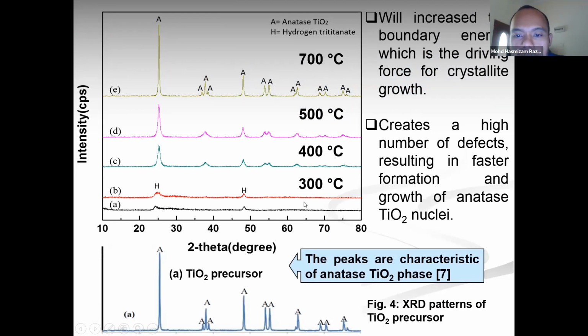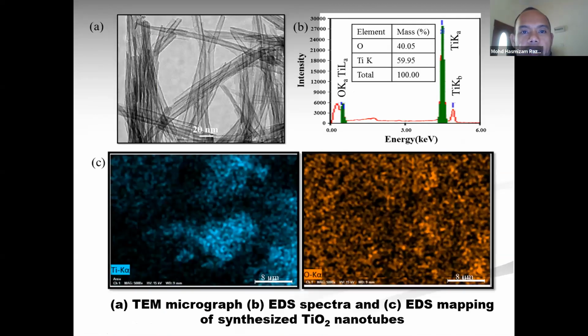Using the XRD analysis, we can claim that at 300 degrees C after calcination, we obtain hydrogen titanates. After 400 degrees C calcination, we can observe the formation of anatase titanium dioxide. This is the TEM image and EDX analysis of the sample after calcination. We can observe the formation of hollow elongated nanotube structures, very good nanotubes, with a diameter of around 6 nanometers.